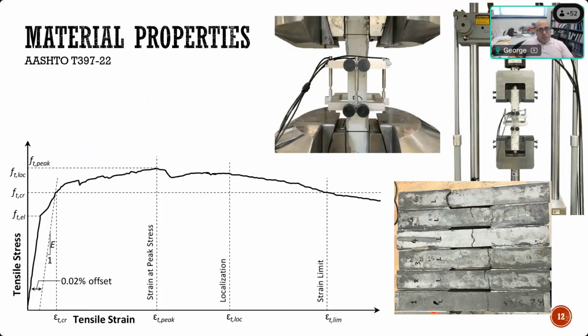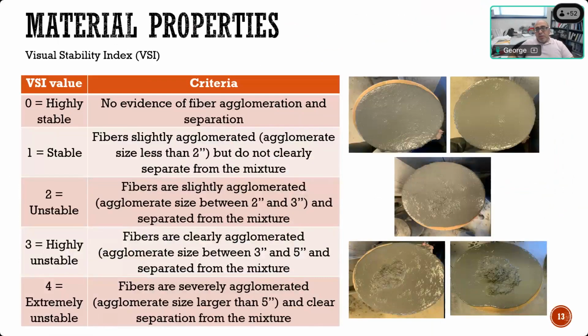So these are the mechanical properties that are very important to test for, so you can know if the UHPC that you have and you're going to use meets the requirements according to AASHTO or according to specific project requirements. After that, there's also something very important, in my opinion, for UHPC. It's not just a mix and adding the fibers. You want to make sure that the fibers are stable in the concrete, very similar to the idea of having self-consolidating concrete, where you want to make sure the coarse aggregate is well distributed and stable in the mix.